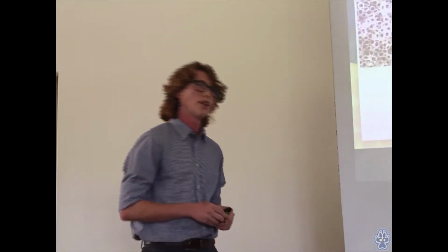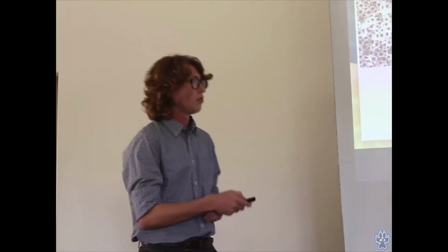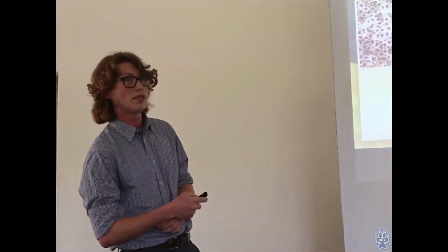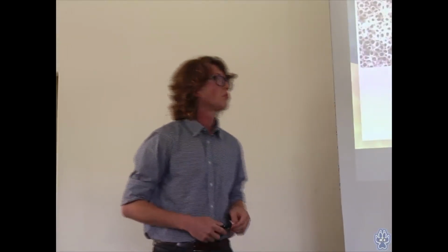So by leaving this on the surface, we know that we can preserve that order through a second anodization. And so right here, if you can see in this image, we have this idea that we can grow these nanotubes straight up. So here are my results up here. This first image is after the first anodization. You can see these nanotubes don't really have any particular direction. And this second image is of our oxidation removal.